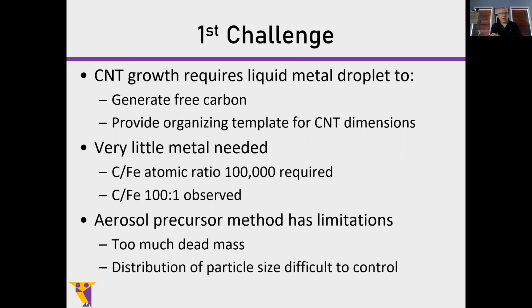And so using the aerosol precursor method produces dead mass. It produces particle sizes that are difficult to control. So the first challenge is, how do you generate a metal particle of the right size, the right composition, so that it doesn't aggregate and form dead mass, which is chemically inert?